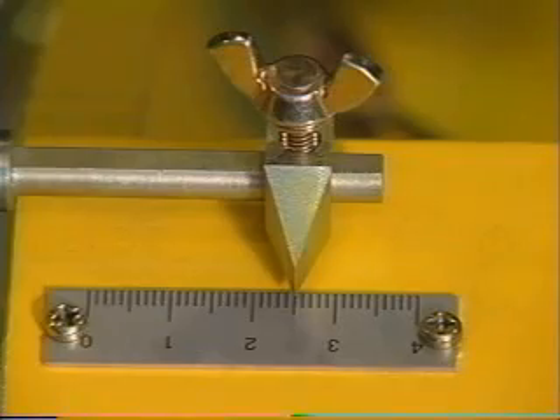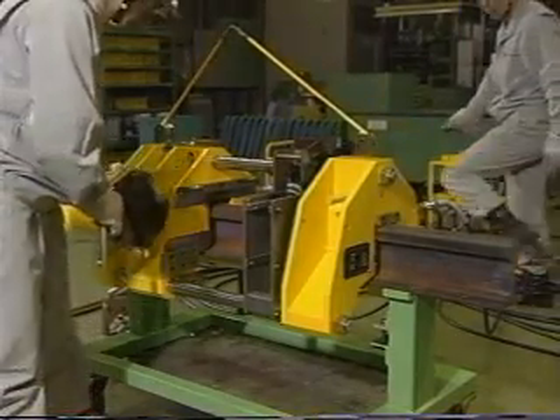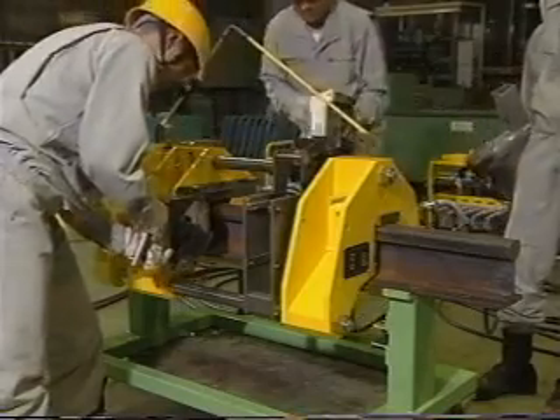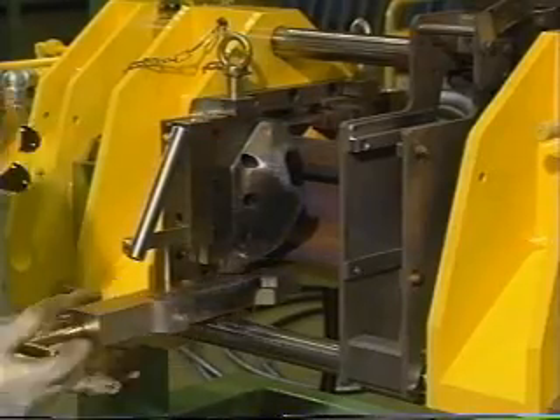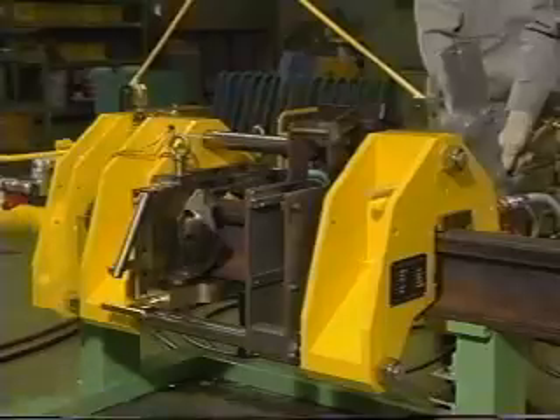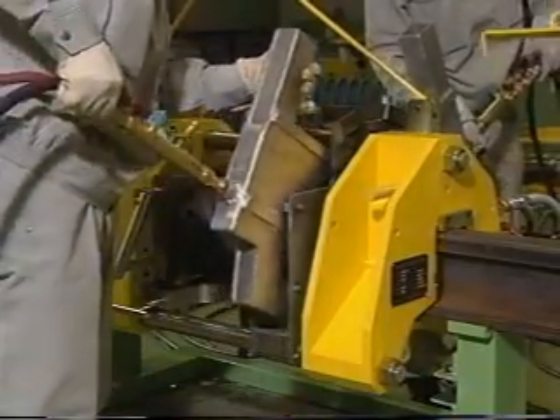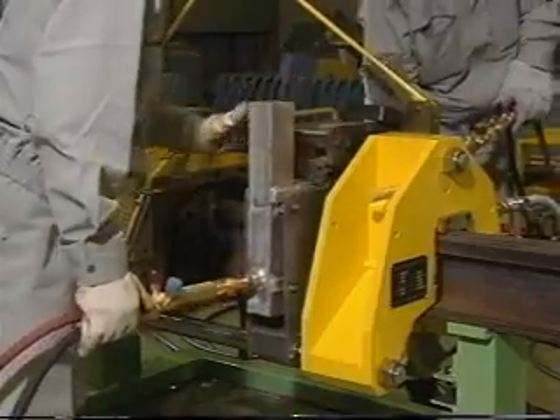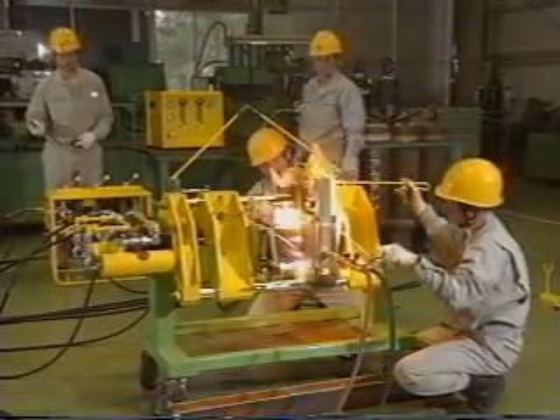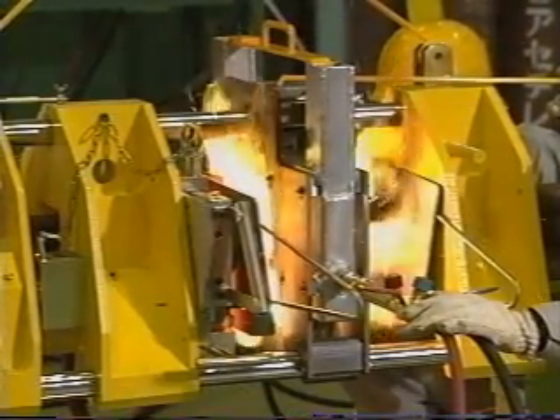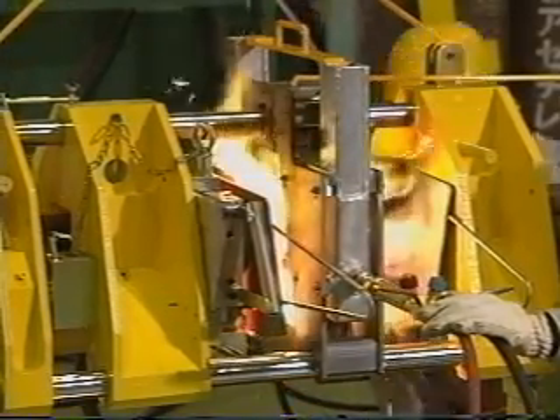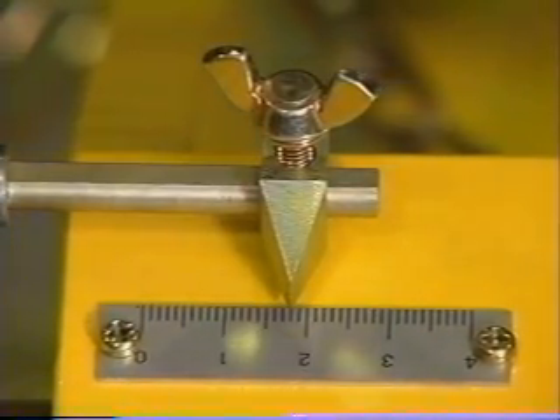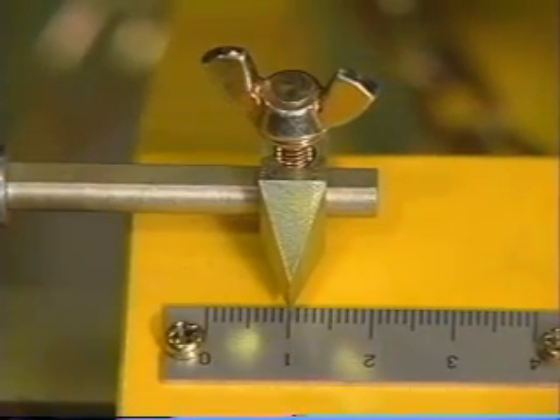After setting the trimmer on the rail, the burner is set. Ignite the gas with the burner away from the end faces. Make an adjustment so that the flame of the right burner is uniform with that of the left burner. Continue heating and perform pressure welding while the burner is moving along the pressure welding gauge. Perform buckling at 10 mm before the prescribed pressure welding gauge.